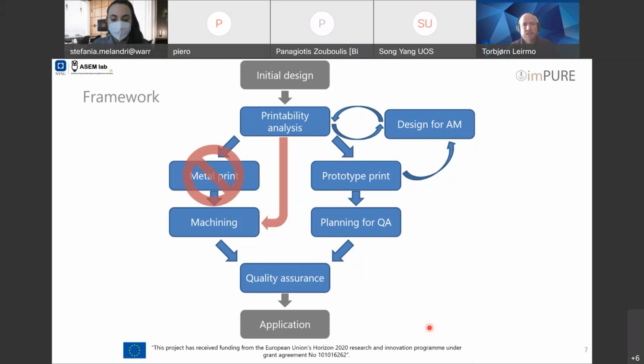Now, there's also a possibility that this printability analysis shows that this part shouldn't really be printed at all. So this means that you should go straight to machining, and this gives some flexibility to the framework. But beware that if the machining is still quite extensive, you have the possibility to go through this prototyping part and be able to enhance this or do this quality assurance more swiftly after all. For instance, as I mentioned with the fused filament fabrication technique, you are able to produce a prototype within 6 to 7 hours, depending on the geometry, which means that this quality assurance can be done much quicker.